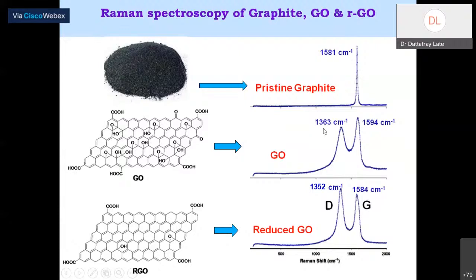Once we have graphene oxide, because now you lose the graphene, right? A lot of functional groups. You can see there are a lot of other functional groups, OH, oxygen, OH, and all these things. What happened? We are actually adding defects in the sample, right? So this comes as a band known as the D band, which comes around 1363 centimeter inverse. And you can see this single peak of pristine graphite changes; the FWHM of this particular spectrum also changes, and the position of the spectrum also changes.